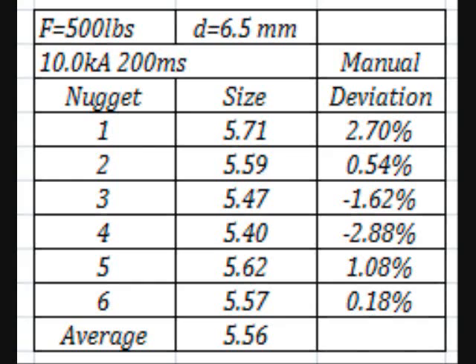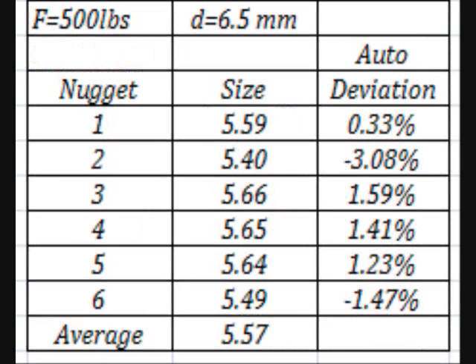This is to program a welder with 500 pounds, 6.5 millimeter, 10 kiloampere, and 200 milliseconds. When we took 6 welds and averaged them, we got 5.56. So this is our program, okay? Once we go into auto mode, we make 6 welds, 2 coupons, and the average is 5.57. Compared with the manual weld programming, which gave us an average of 5.56, this is extremely close.